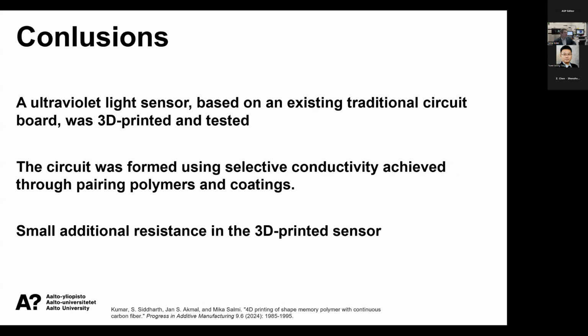So we were able to 3D print this sensor board for this ultraviolet light sensor, and then this was selectively conducted. So that would, in the end, mean a much more automatic process. If we could print the parts and then put them in the ALD reactor, we can get the circuits out ready. There was some additional resistance in the 3D printed sensor, but that wasn't very significant.